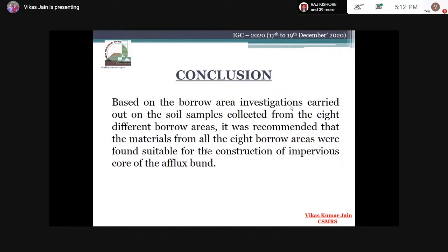This is the conclusion: based on the borrow area investigation carried out on the soil samples collected from the 8 different borrow areas, it was recommended that the material from all the 8 borrow areas was found suitable for the construction of the impervious core of the dam. We should also note that 7 to 8 soil samples fall under the CH group. Care should be taken while doing construction for the CH group. Care should be taken by the project authority.